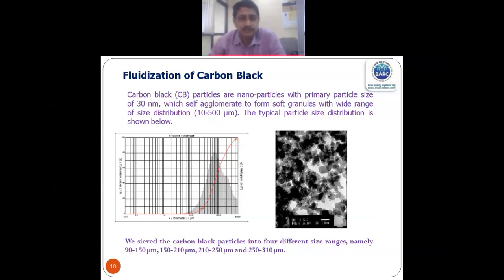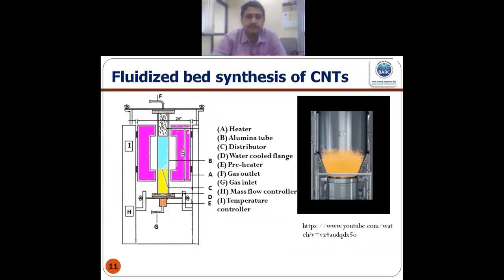But carbon black is such a wonderful material where the primary particle sizes are in the nano range, in the range of 30 nanometer, and they self-agglomerate to form a soft granule in the range of 10 to 500 micron. And if we sieve them in the proper size range, it is easily fluidizable. Carbon black is cheap and fluidizable. So that is why we have used carbon black as the support material.